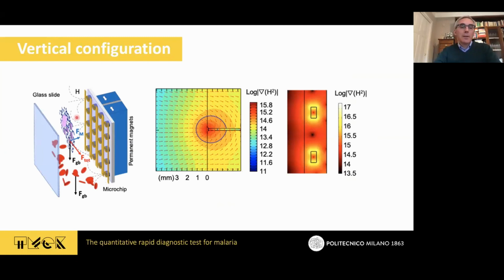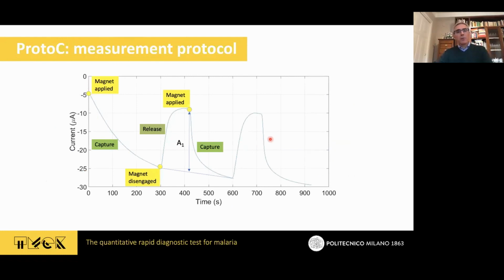This way, what happens? The particles are sedimenting, flowing down due to gravity, but during this motion, they are captured. They are attracted by the external gradient and by the local gradient generated by the nickel posts. And in this way, we can separate particles and also measure them. And this is just a summary of the field produced by our magnetic arrangement. And this is our protocol for measurement.